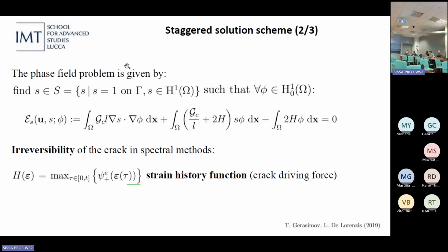For the phase field equation, so the evolution of the damage, we have this variational problem here, and we can see that this is a sort of diffusive part. It involves the gradients, and this H here is the source of damage, the so-called strain history function, or crack driving force. It is coupled with the internal strain of the material, and this accounts for the irreversibility of the crack. Of course, the crack can only advance inside the material.